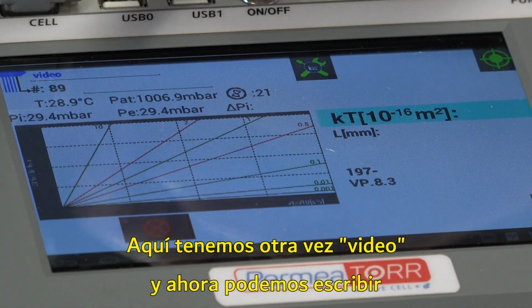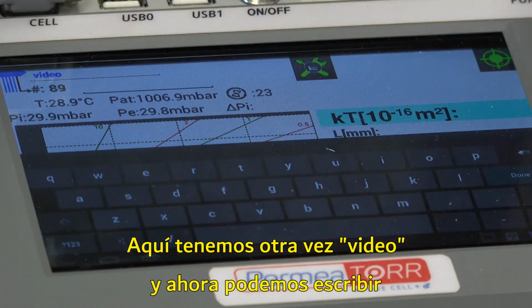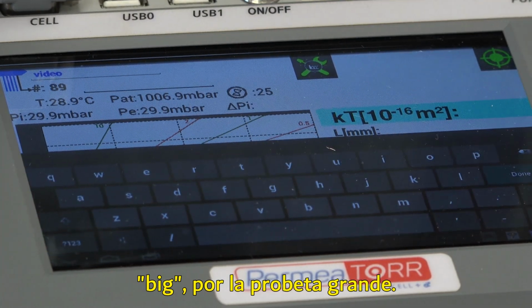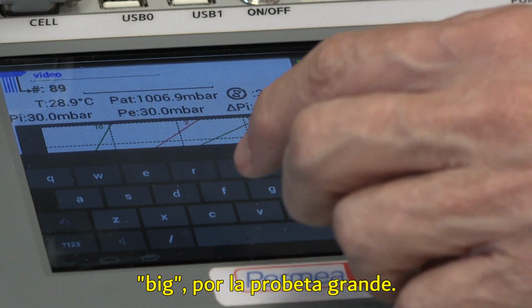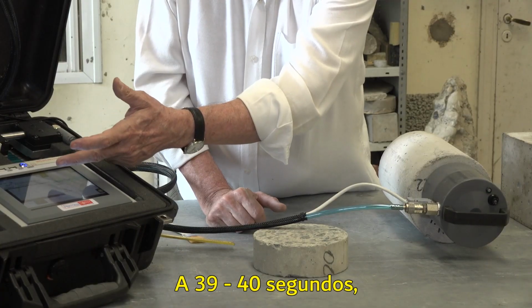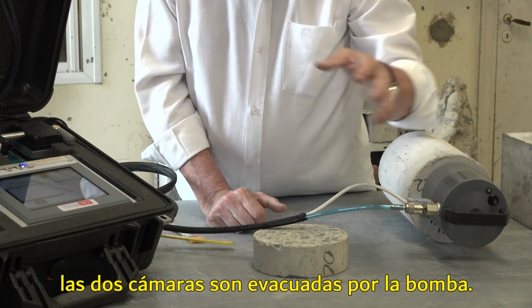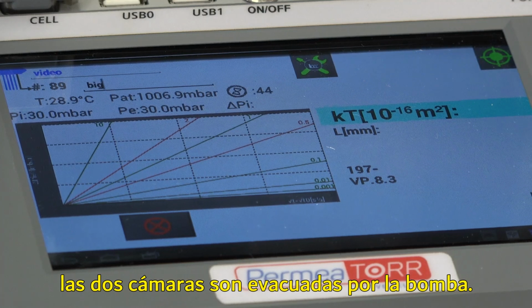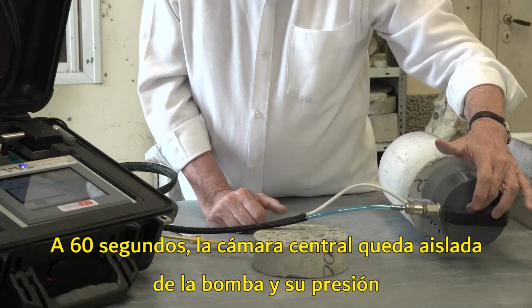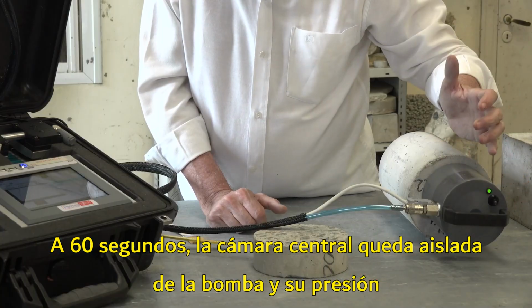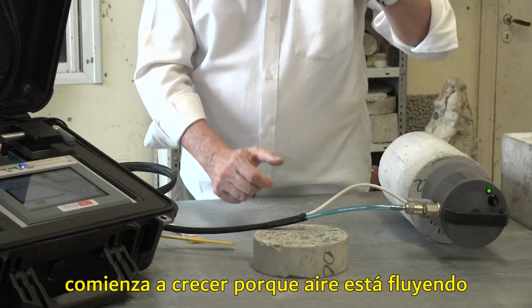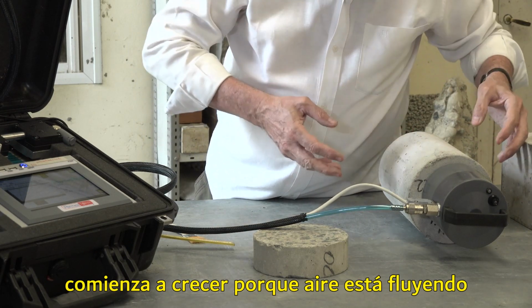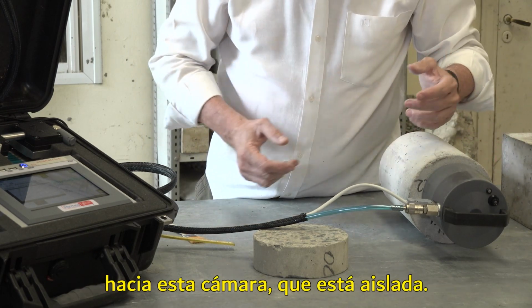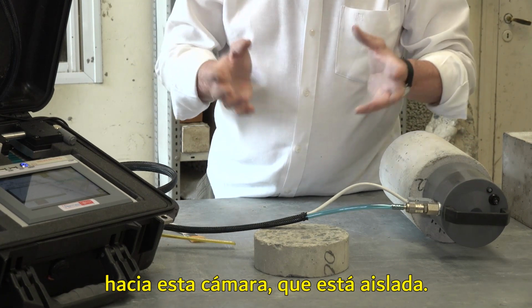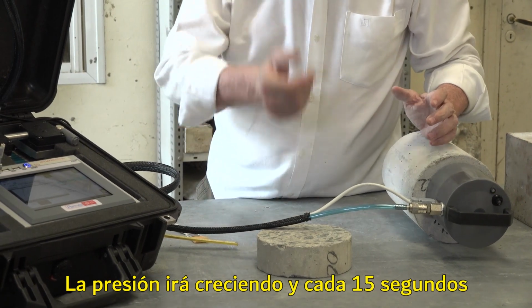So here we have again video, and we can put now, I don't know, cylinder or the big sample. There are 39 seconds, 40 seconds. At this moment, the two cells are evacuated by the pump. At 60 seconds, as I said, the central chamber is isolated from the pump, and then the pressure starts to grow because air is flowing into this chamber, which is now isolated, and then the pressure will grow.